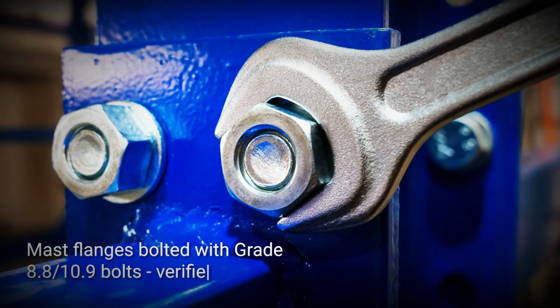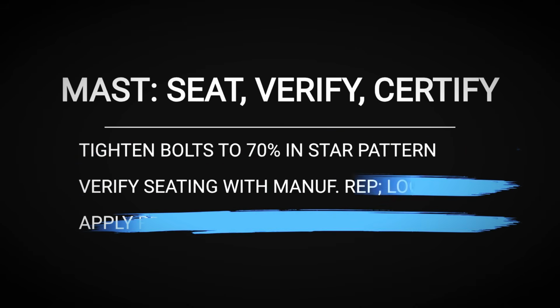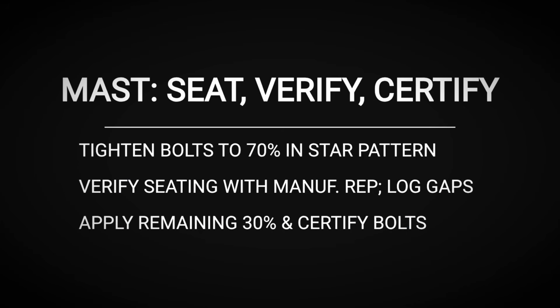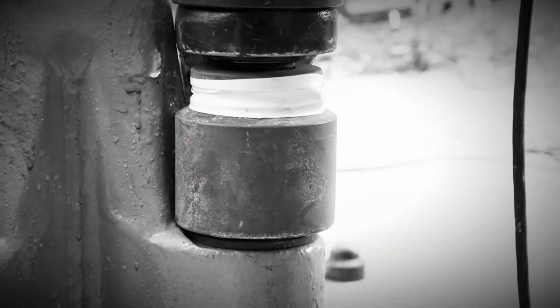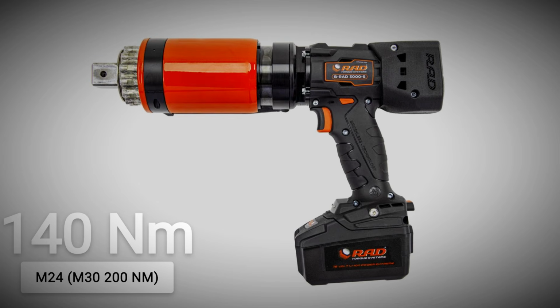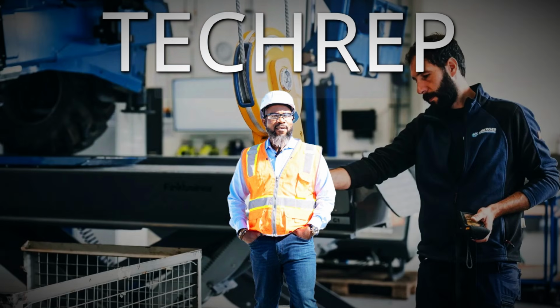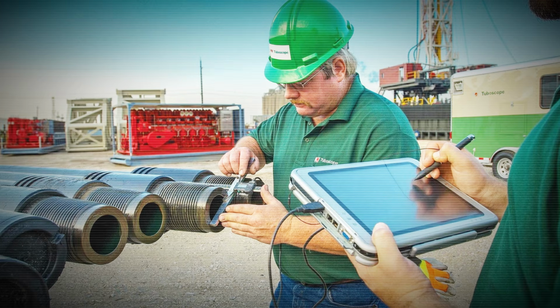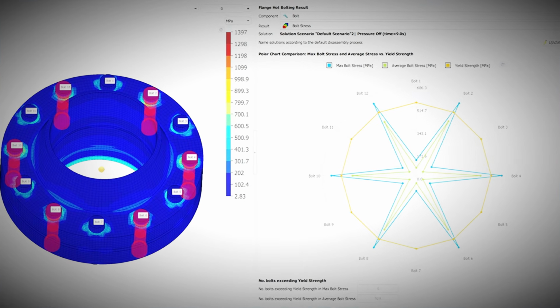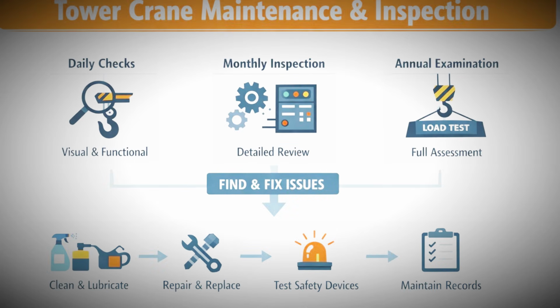High tensile bolts, usually grade 8.8 or 10.9, secure each flange connection. The bolting process follows a two-step torque protocol. First, all bolts are tightened to 70% of the final specified torque in a star pattern to seat the flanges evenly. Then, after verifying uniform seating, the remaining 30% is applied, bringing each bolt to its full rating, often 140 Newton meters for M24 bolts or 200 Newton meters for M30 bolts. A manufacturer's technical representative oversees the process, logging every torque value for quality assurance. This bolt log becomes part of the permanent record, ensuring traceability and compliance with both engineering standards and safety regulations.